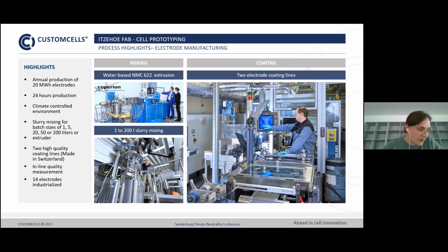Some more words about what we are doing at Custom Cells here. The process of lithium-ion battery production starts with mixing the active materials, conductive additives, and binders to a so-called slurry, and then the application of this slurry to the substrate foil. And this mixing can be done in various ways. You can do this continuously, which we do on this extrusion machine, where you have a continuous mixing of all these materials and you get a continuous production of slurry.